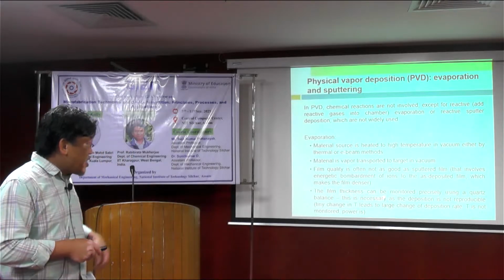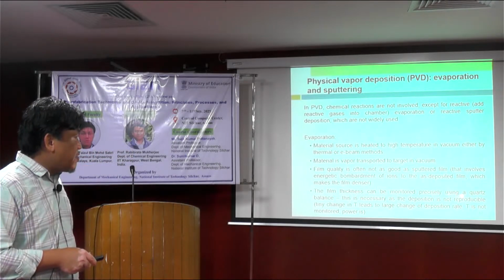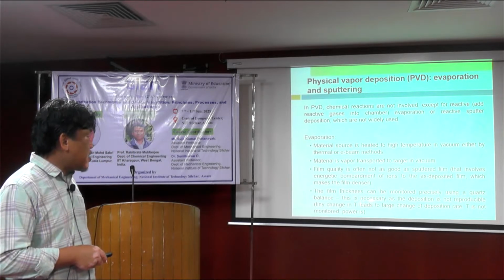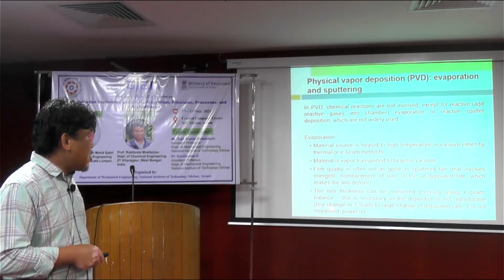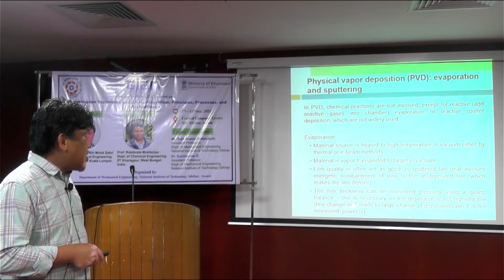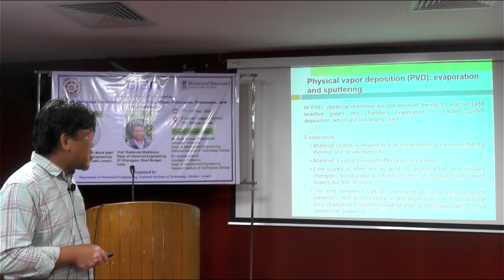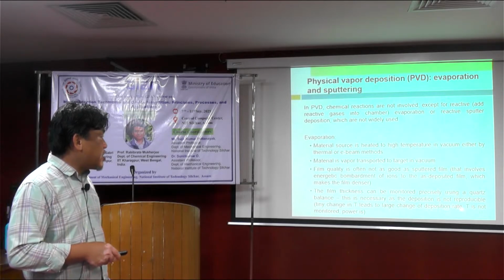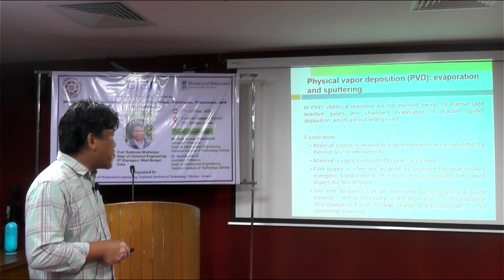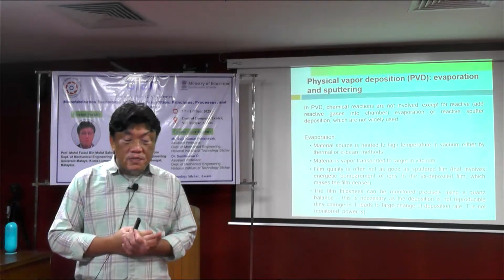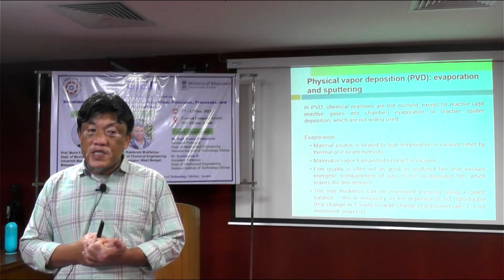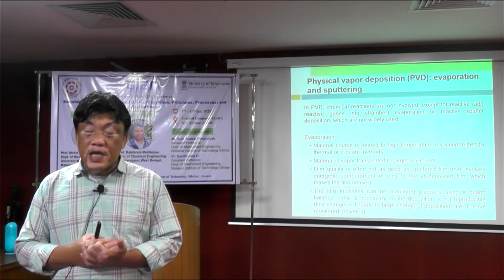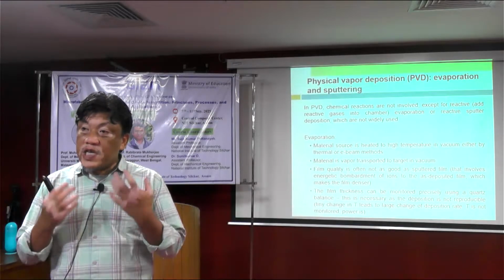The film thickness can be monitored precisely using a quartz balance. This is necessary as the deposition is not reproducible, and a tiny change in thermal leads to a large change of deposition rate. Temperature is not monitored, power is, because in evaporation, basically we supply the current to the heater.